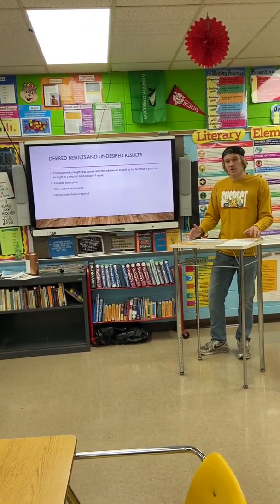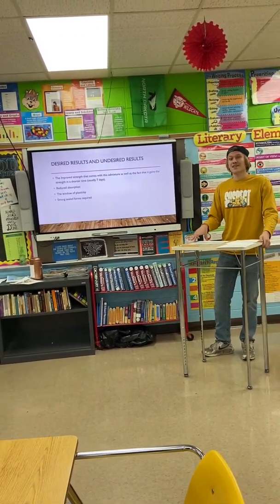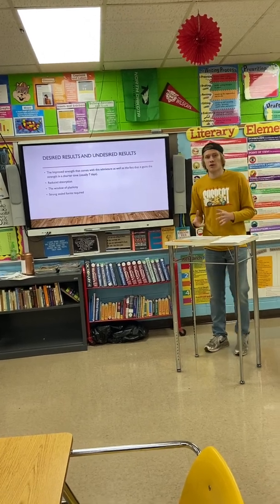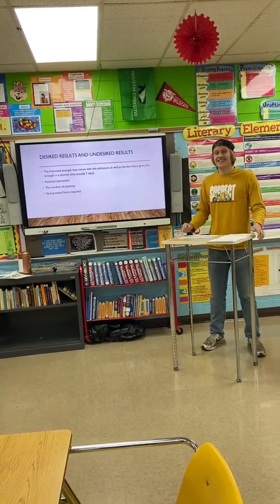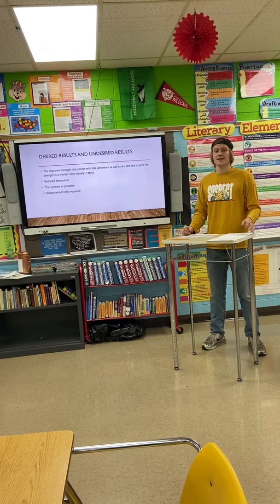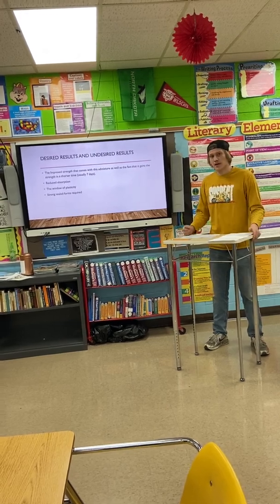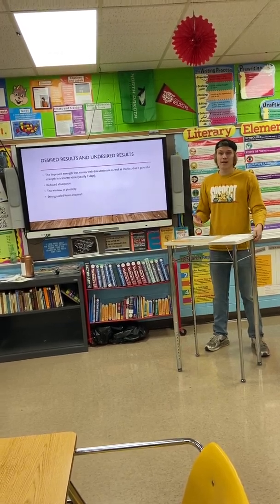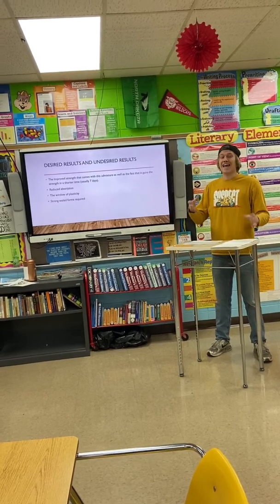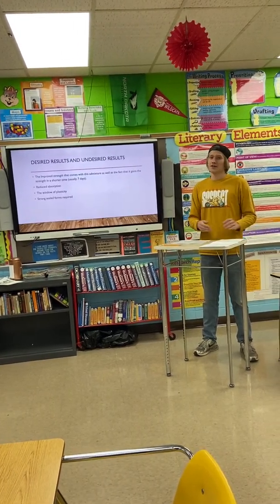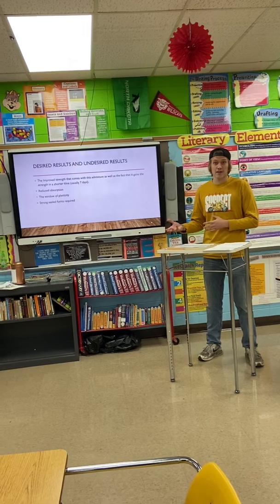The problems that come with it are the window that the concrete does stay more plastic and workable. It's typically only 30 to 60 minutes that the concrete stays in its liquid flowing form. That is why this plasticizer is usually added while the concrete is being mixed at the job or pour site, not while it is at the batch plant before it leaves.